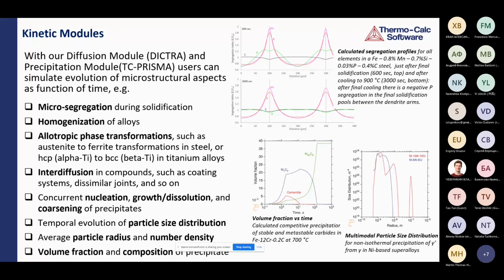Using TC-Prisma, you can also predict the concurrent nucleation, growth, dissolution, and coarsening of precipitates, and also predict the temporal evolution of particle size distribution, and also get the average particle radius and number density, volume fraction, and compositions of the precipitates.